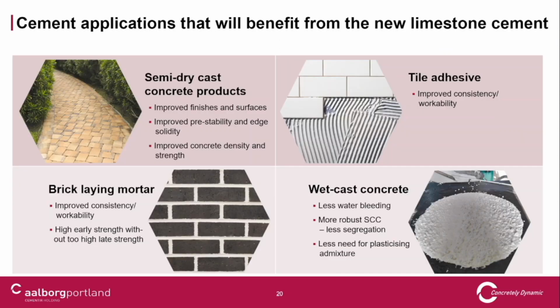This is based on what we've done in the laboratory, but also on our long-term experience with limestone-filled cement in Denmark—we started back in '95 with the first limestone-filled cement. What we see is that for semi-dry cast concrete products, this type of cement will be very good.